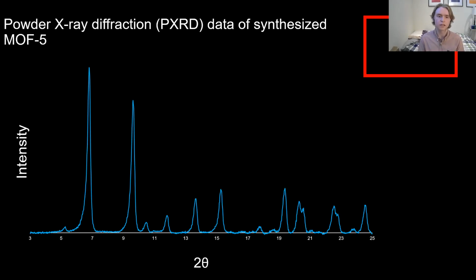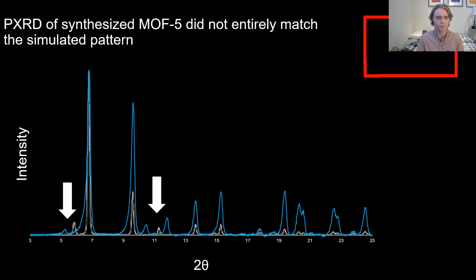Now I can actually go ahead and show you some of my powder X-ray diffraction data of the MOF5 that I synthesized. So note again that we have 2 theta on the x-axis, and then on the y-axis we have intensity. I don't have any units here nor numbers. It's not particularly important what the absolute intensity value is here. What's more important is, for 1, peak location, and for 2, the relative peak heights between the different peaks in the framework. So I was able to get this spectra of my MOF5, and then I actually went ahead and compared it to some simulated spectra that I was able to find in the literature.